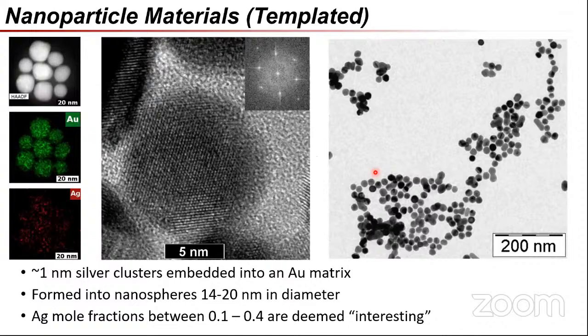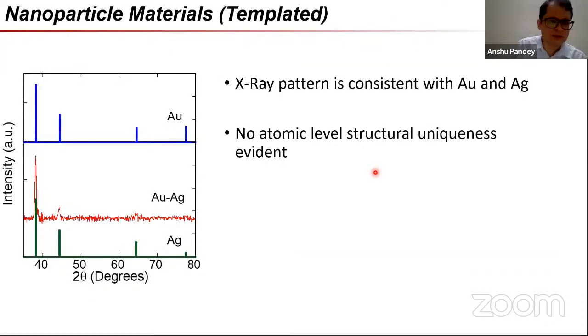So, moving onward, we see that the lattice structures of these are not altered. Silver gold has essentially the same lattice structure as gold silver. So at least if we say that there is some atomic level uniqueness creeping into the structure, it does not appear to be the case.